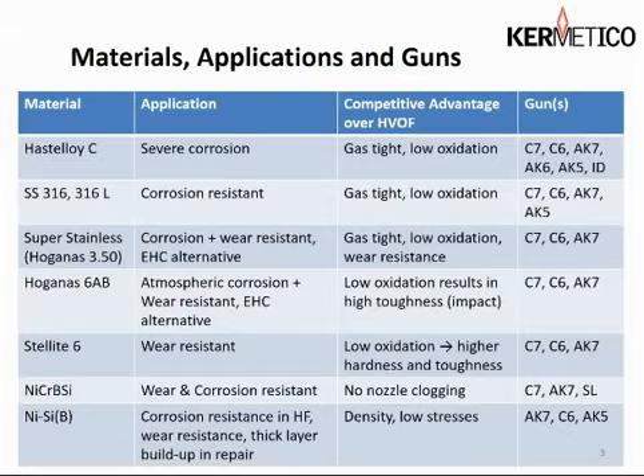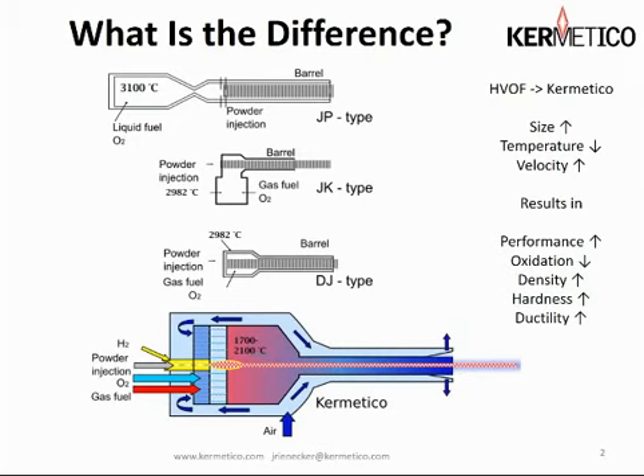And then enter our color diagram of our HVAF-C, or convertible gun. First up, you'll notice that we have a ceramic element here in the combustion chamber. Gases are delivered behind it, and they exit through literally hundreds of tiny itty-bitty holes. So the flame is spread out over the entire face of the combustion chamber, and they're very small. So combustion is taking place very close to the ceramic element, and by the time you get down to transitioning to the nozzle, combustion is complete.